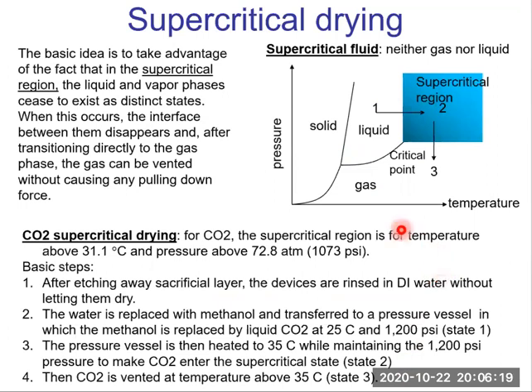We can also avoid stiction during releasing using supercritical drying. The basic idea is to take advantage of the fact that in the supercritical region, the liquid and vapor phases cease to exist as distinct states. When this occurs, the interface between them disappears, and after transition directly to the gas phase, the gas can be vented without causing any pulling-down force.